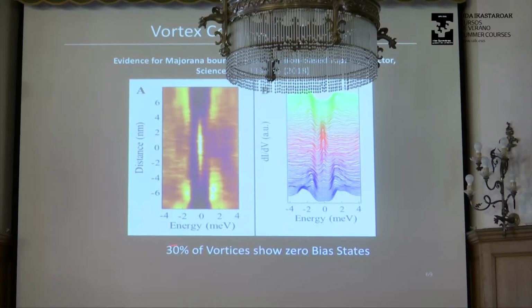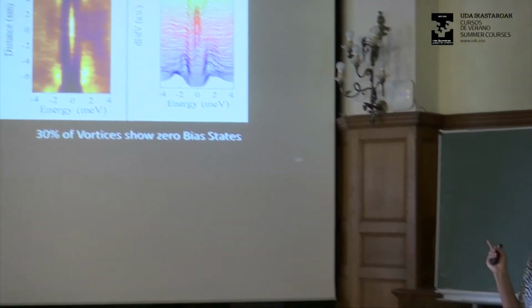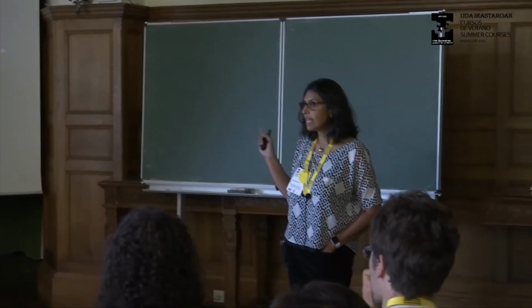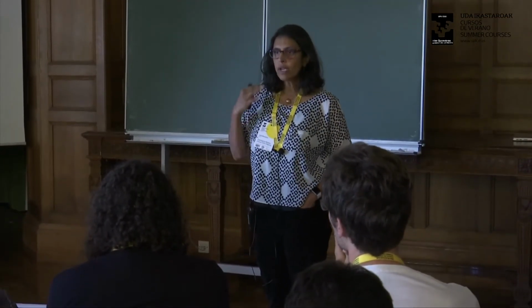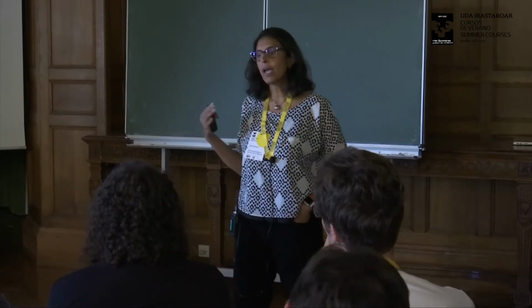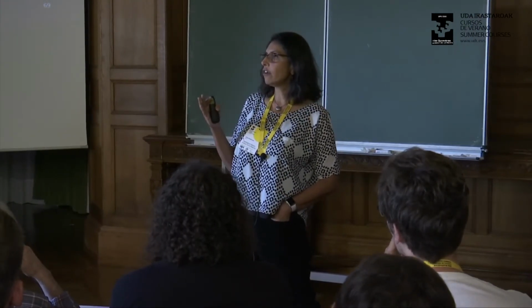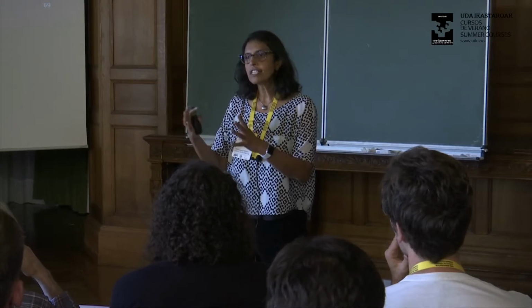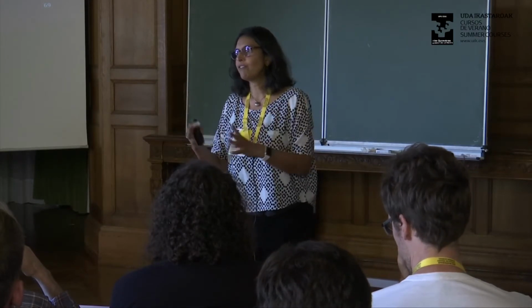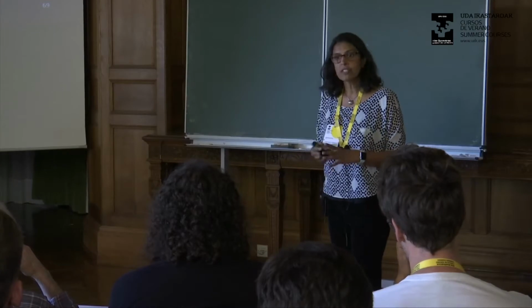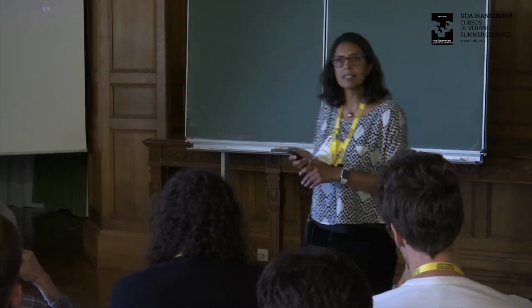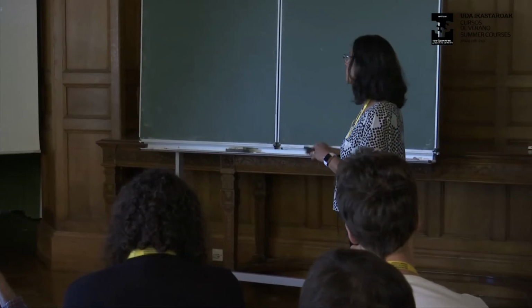However, in their work, only 30% of the vortices showed 0 bias states, so there was still a question about what's going on in this system. Hanaguri has done more recent work on the same material, where he shows that at very low temperatures, if you can decrease the magnetic field, you can get up to 80% of the vortices showing bound states very close to 0, which are within resolution. His resolution at 100 millikelvin is pretty good, within resolution at 0 bias. So this does seem like a pretty interesting system.